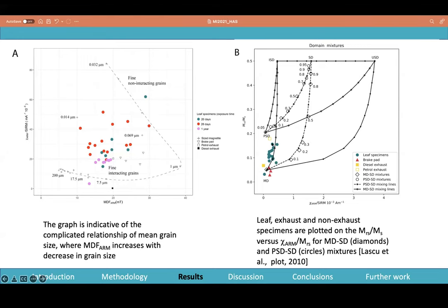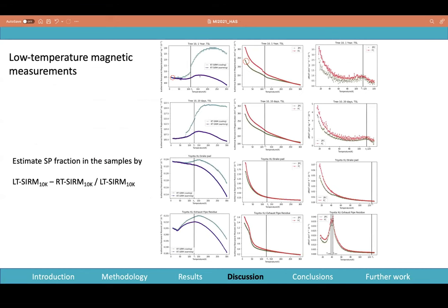We also plotted our results on a Lascu plot, which is an alternate kind of plot for grain size distribution. Here is ARM susceptibility normalized over SARM, the same axis as this figure, and this is the MRS over MS on the y-axis. You can see how our leaf specimens plot on the interacting single domain and multi-domain line, which is in agreement with this particular figure. But then you can also see our brake pads plotting somewhere over here near the MD region. So this is where the FORCs would come in, and just before going to the FORCs,